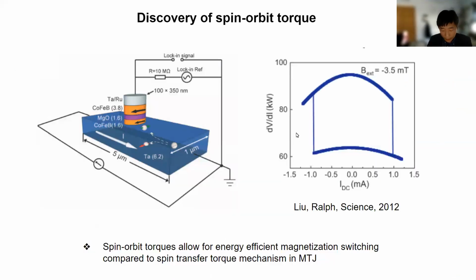Okay, so the spin orbit torque was one of the first experimental studies that demonstrated that you can use the spin current produced by spin Hall materials to switch the magnetization of a magnet that is overlaid on top of that spin Hall material. What was done in this experiment was the application of an electrical current. And what they observed is that with the application of electrical current, they saw a switching of the magnetization of this nanomagnet.